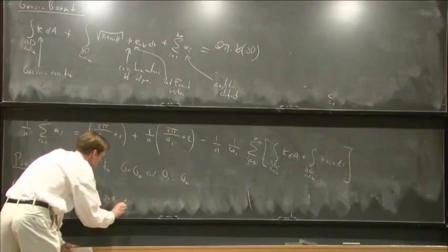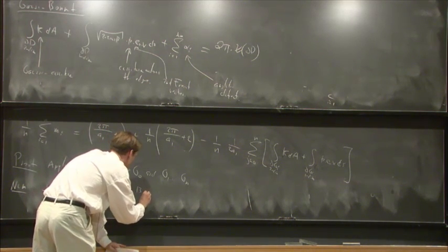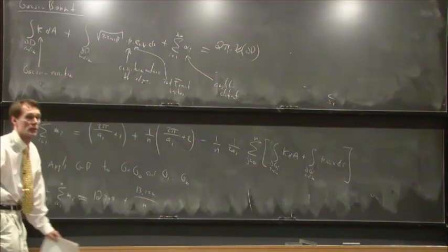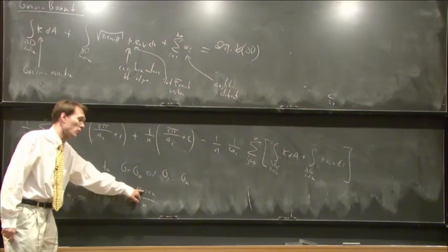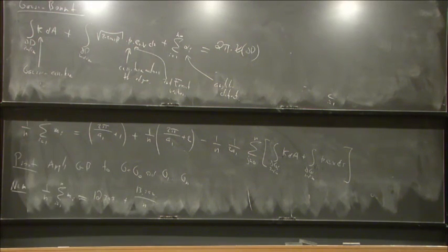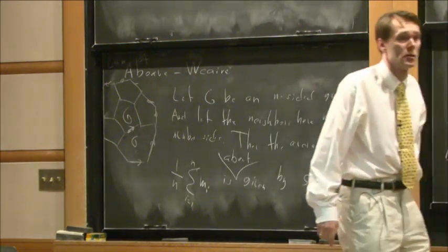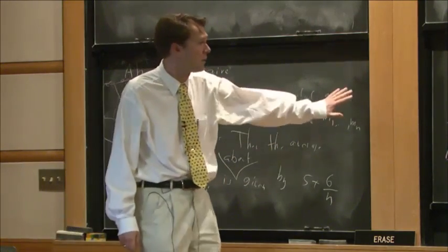12.397 plus 13.397 over n. Okay? And the nice thing to compare here is that the two constants appear to differ by 1, and it's just like in the original law, it's 5 and 6; here you add 1 to 12, you get 13. So it's nicely fitting. Okay? So there's the three-dimensional law.